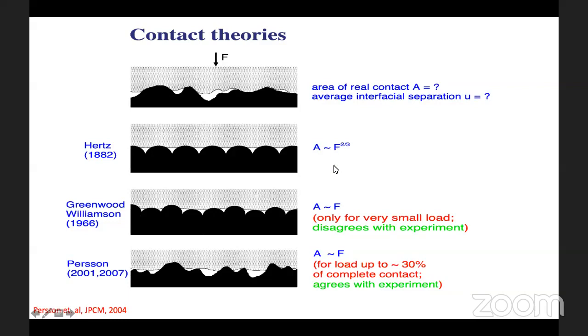What Greenwood and Williamson did in 1966 was that in their theory, they had spherical bumps, but with Gaussian fluctuation of their heights. So the heights have a Gaussian distribution. There is a random distribution of heights according to the Gauss distribution, and when they studied the contact, they found that the area is directly proportional to the normal force, but only for very small loads. These Hertz and Greenwood-Williamson models are what we call asperity theories in contact mechanics.